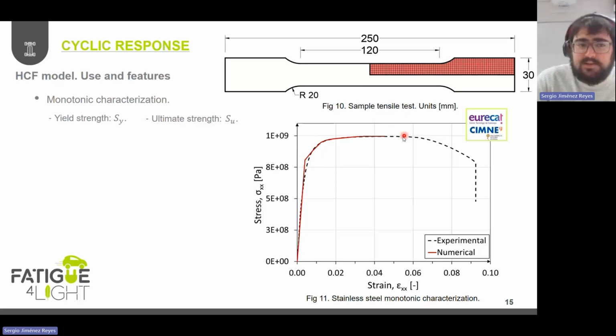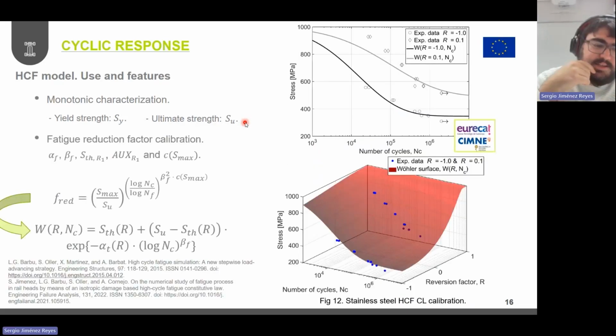So from this type of analysis, basically what we are obtaining here is that we are calibrating our yield strength, the ultimate strength, but also the Young modulus, the Poisson ratio, and the fracture energy of the material. Then once we finish with this, we can move towards the calibration of the fatigue part of this high cycle fatigue constitutive law, which is based on characterizing the parameters that define this fatigue reduction factor function, which has this form here. This is the mathematical expression that governs this degradation in terms of strength and fracture energy. And in order to calibrate this function, it depends on 5 parameters, these 5 parameters here.